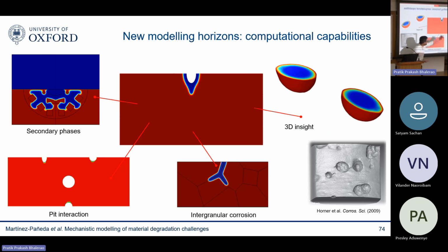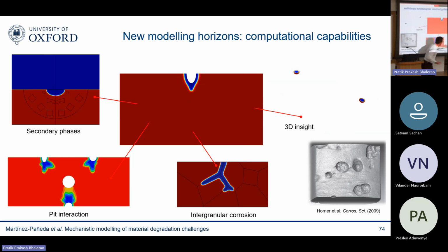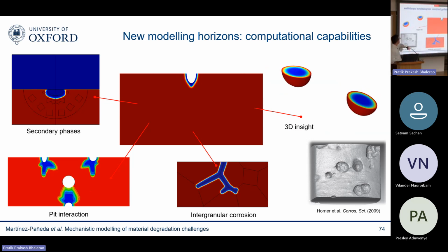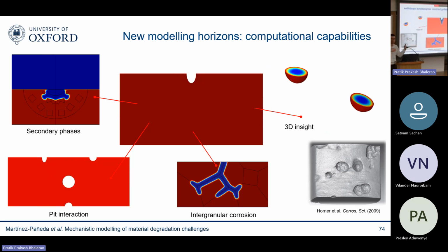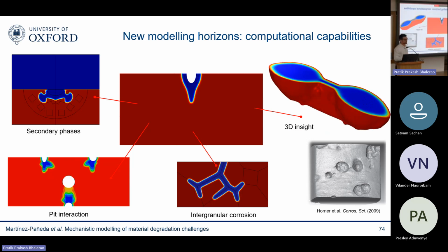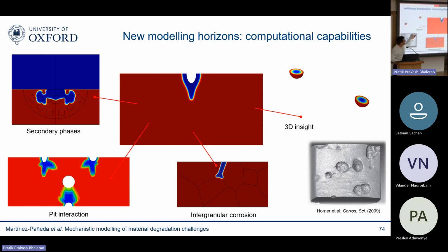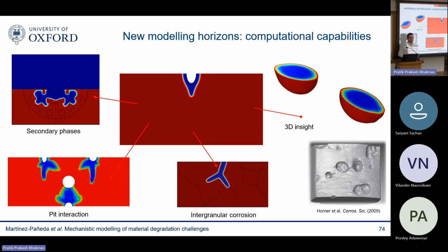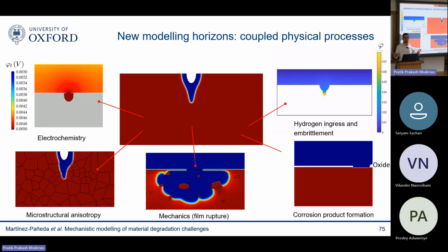So you may have secondary phases that are insoluble, interaction between multiple pits, intergranular corrosion. We recently did some XCT 3D observations and saw some very interesting phenomena. We can again rationalize this with this. And it's not only the computational things that you need to do, it's also the physics, right? There's a lot of things happening in corrosion. You may have an influence of the electrochemistry, but again, we can solve those equations describing the electrochemical behavior of electrolytes. You may have microstructural anisotropy. Again, you can couple this with crystal plasticity, with microstructural descriptions of your material.